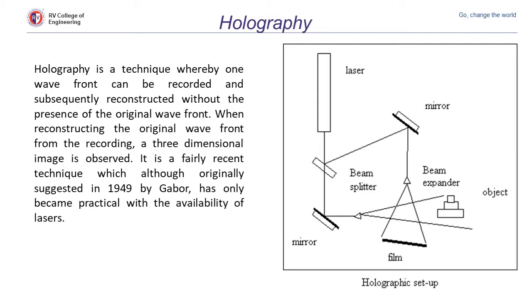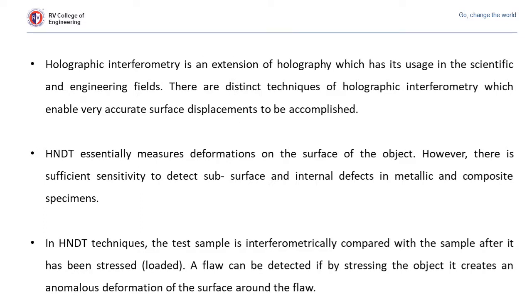It was a fairly recent technique and it originated in 1949. Holographic interferometry is actually an extension of the holographic method and it is used in engineering fields. These distinct techniques of holographic interferometry enable very accurate surface displacement measurement. The holographic method essentially measures the deformation on the surface, and it is very sensitive to detect subsurface and internal defects in metal and composite specimens. In the NDT technique the test sample is interferometrically compared after it has been stressed or loaded, and the flaw can be detected if the stressing of the object creates an anomalous deformation of the surface.